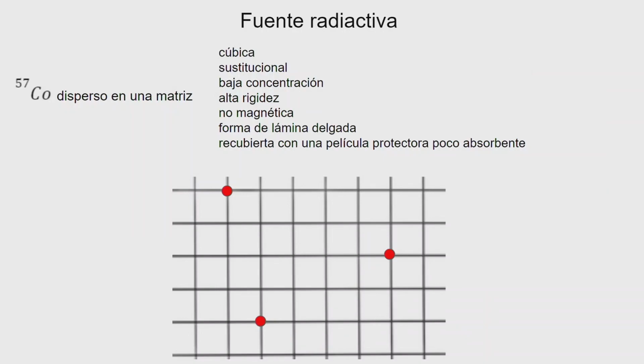And I started now to mention some characteristics of the radioactive source. The radioactive source for iron-57 spectrometry is a source of cobalt-57, which is dispersed in a matrix, usually rhodium. Rhodium is used because it is very rigid, so that the binding of your nuclear probe to the lattice is very good, and you can have decent, very decent Mössbauer recoil-free fractions.